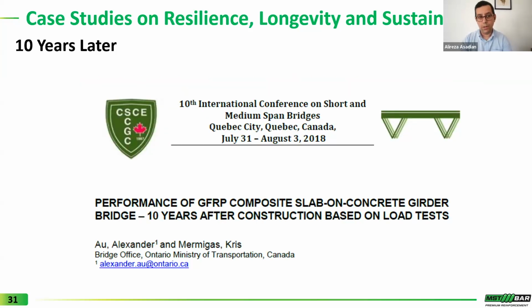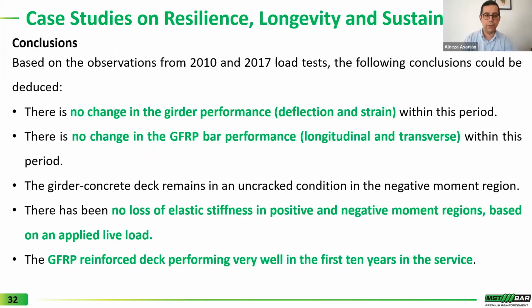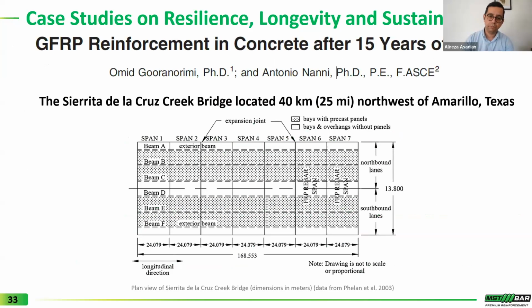Ten years later, MTO did a load testing on the same bridge, and they concluded that there is no change in girder performance within this period. There is no change in GFRP bar performance, both longitudinal and transverse, in this period. Also, they concluded that there was no loss of elastic stiffness in positive and negative moment regions based on an applied live load. And finally, the last conclusion was that the GFRP reinforced deck performed very well in the first 10 years in service. Another case study led by Professor Antonio Nanni is on a bridge in Texas.